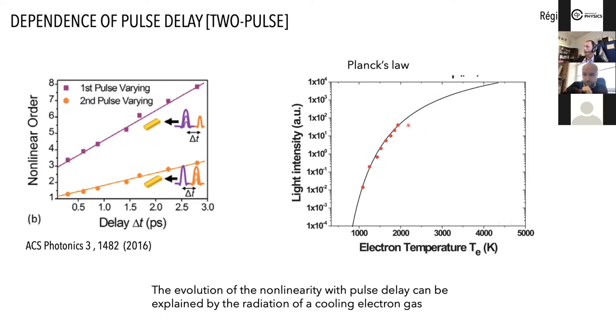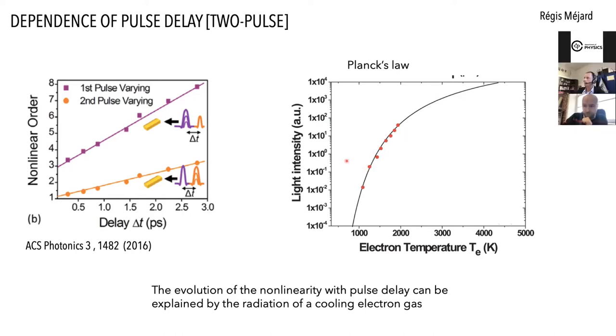And of course, as the electron gas is getting cooler and cooler, you have this very strong nonlinear dependence with electronic temperature that can explain the shape of this curve here. And you see that for long delay between the two pulses, where we're basically probing a cooling electron gas, then we have this nonlinearity order.